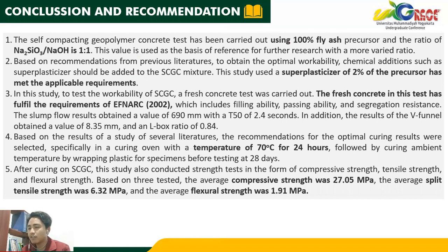And last, after the curing of the SCGC, the study also conducted strength tests in the form of compressive strength, tensile strength, and flexural strength. Based on the three tests, the average compressive strength was 27.05 MPa, the average split tensile strength was 6.32 MPa, and the average flexural strength was 1.91 MPa.